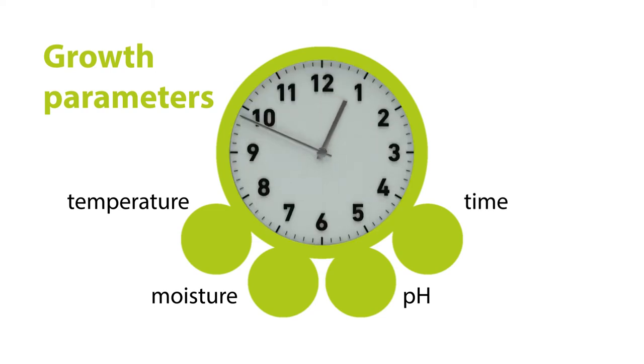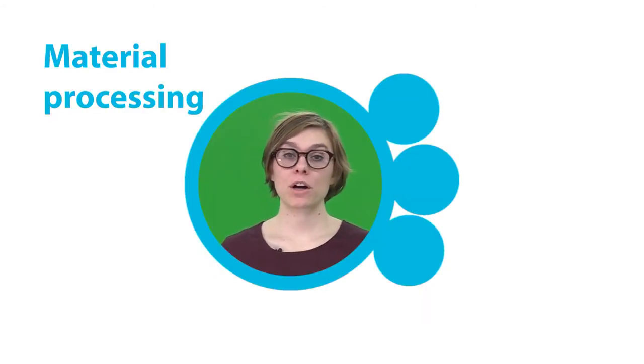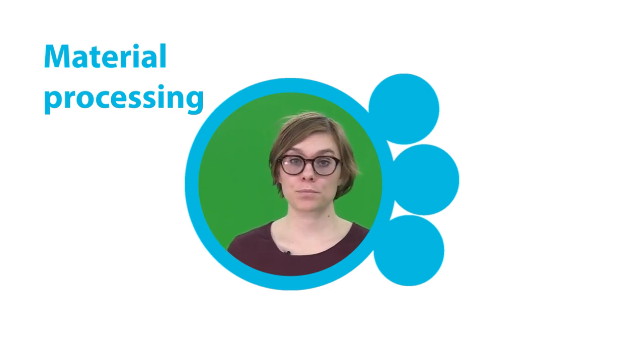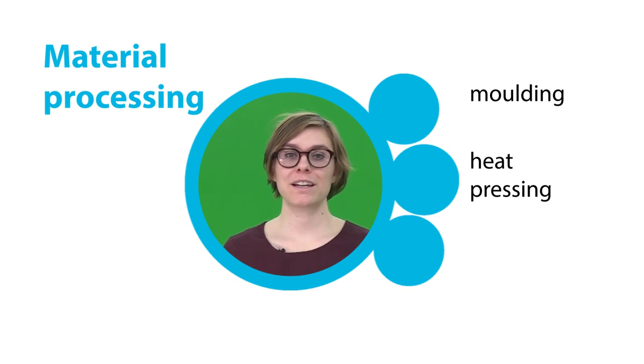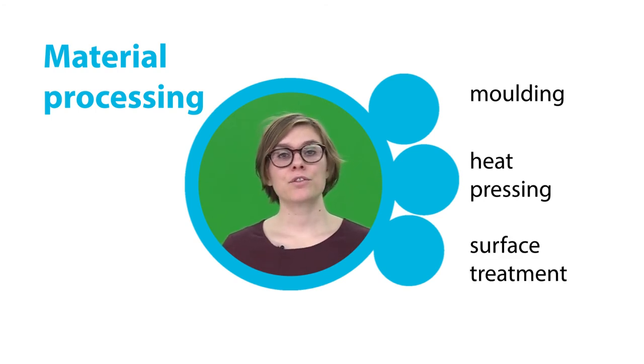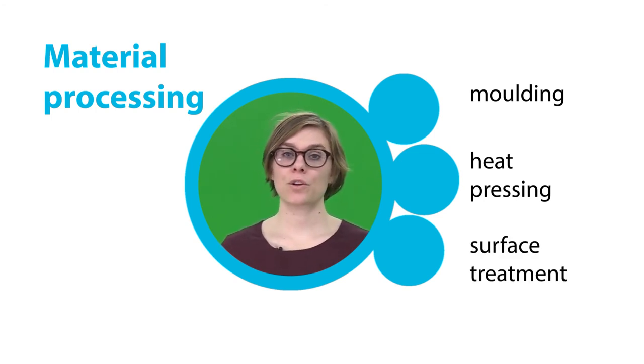When working with microorganisms, the time becomes an important aspect as well. In fact, you need time and patience to let the mycelium do its work. Usually, the period of growth is between 1 and 3 weeks. Generally, the biocomposite can undertake different types of processing, among which we find molding, heat pressing, and surface treatment. The chosen type of processing determines the final obtained product.